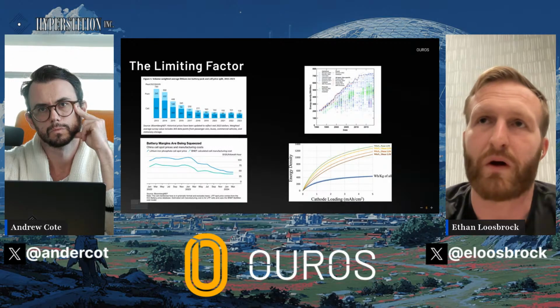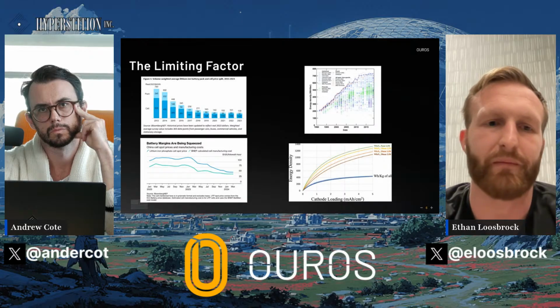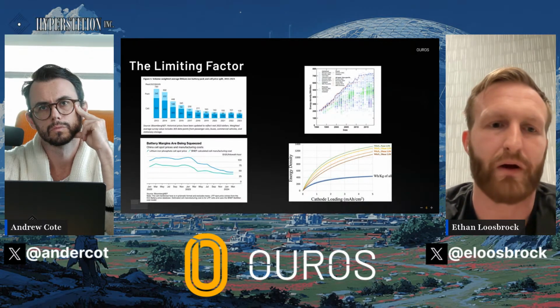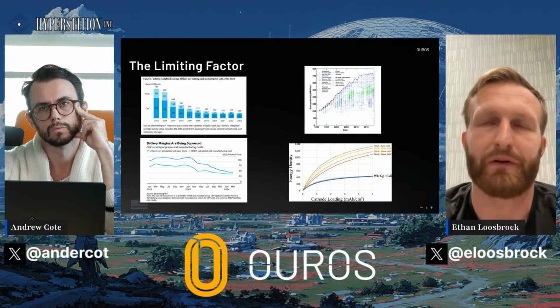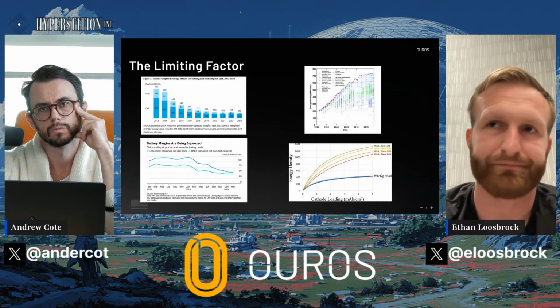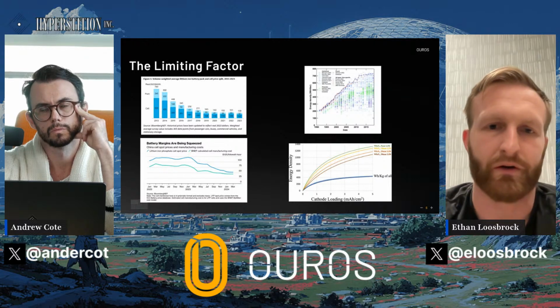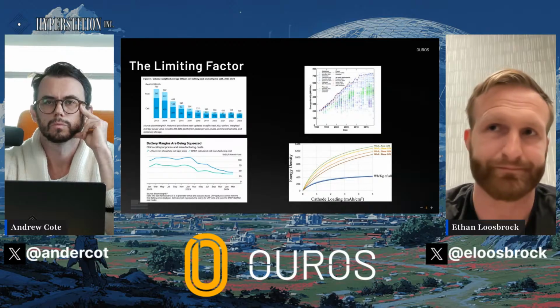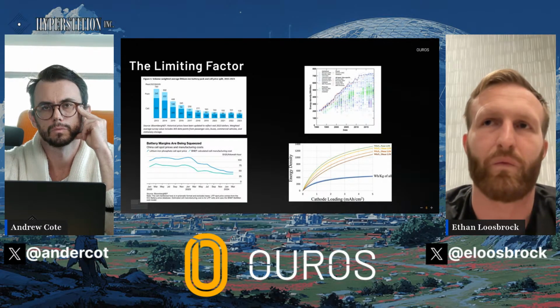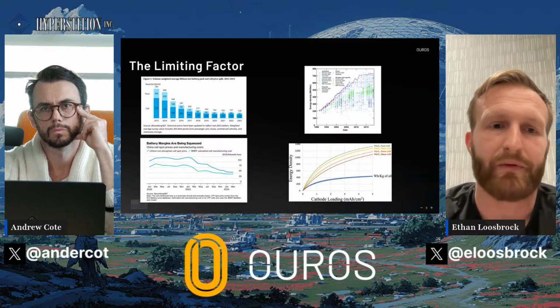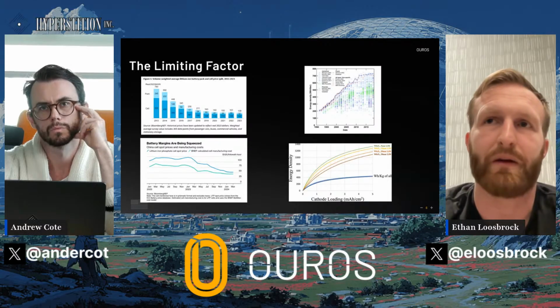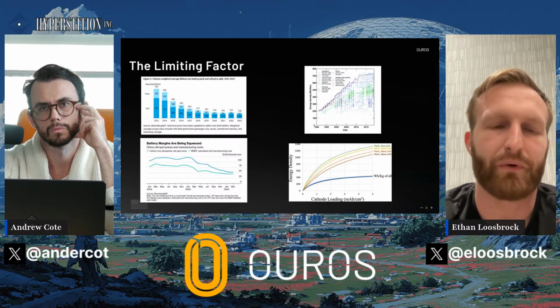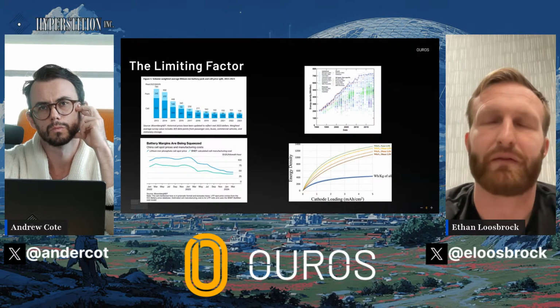One other competitor group of technologies is lithium sulfur. Sulfur is dirt cheap. It's a byproduct of the oil industry. But the way people typically make these cathodes is they mix sulfur with 50% graphene or carbon nanotubes, which are extremely expensive on a per kilogram basis. That's one example of non-scalable materials. In terms of non-scalable processes, I think atomic layer deposition is non-scalable. Chemical and physical vapor deposition are non-scalable. It really needs to be a bulk process. It can't be batch processing. So, continuous high throughput manufacturing processes. Yeah, I think those are the broad strokes.